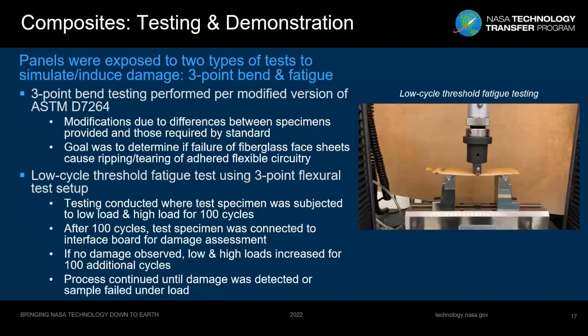The samples that we produced, the test specimens, were subjected to 2 types of testing. They were a 3-point bend and then a low cycle threshold fatigue testing. The 3-point bend testing was per a modified version of ASTM D7264. The modifications were really necessary due to the differences between the test specimen and those that are required by the standard.